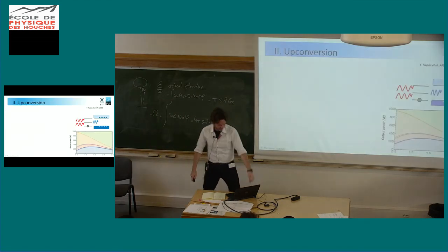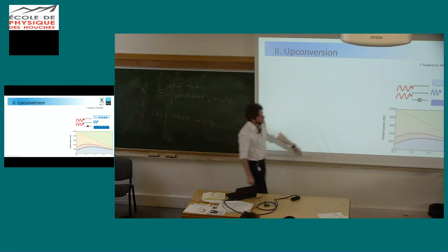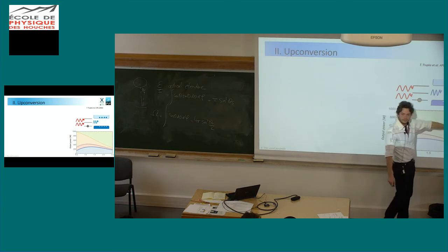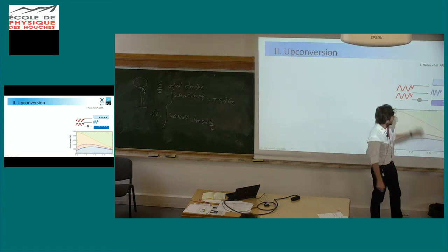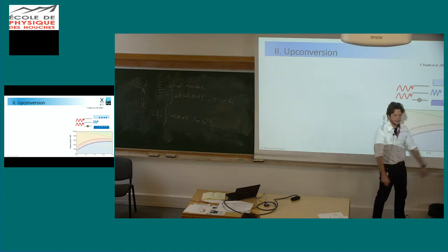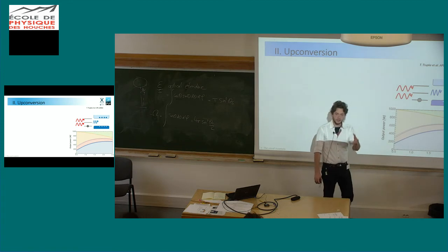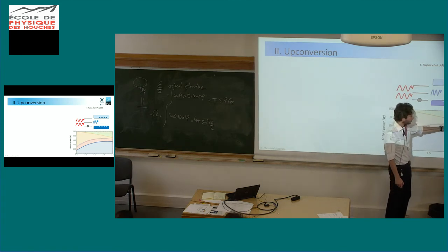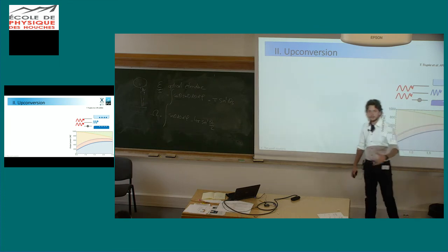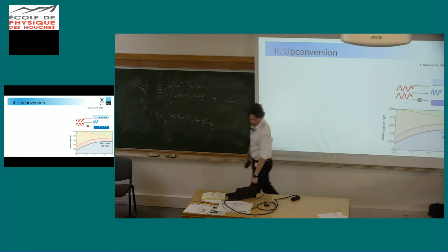So let's see. Upconversion is doing this, essentially. You had photons which used to be not absorbed. They were red photons at a high band gap, so you're losing them. And now you're turning them into blue photons, so you manage to collect them. Okay? And basically, if you remember what we said about concentration, this red line here tells you how much additional power you can win if you make this idea under concentration. So these here are the typical maximum efficiencies which you can get.